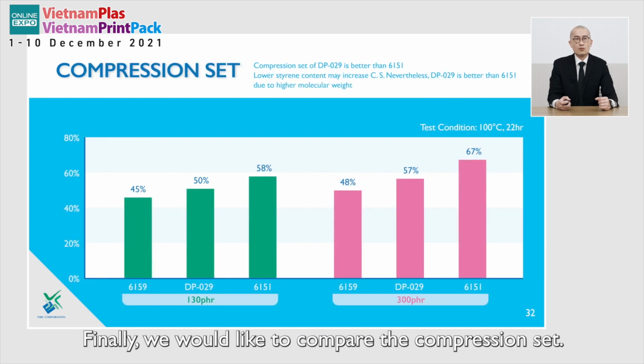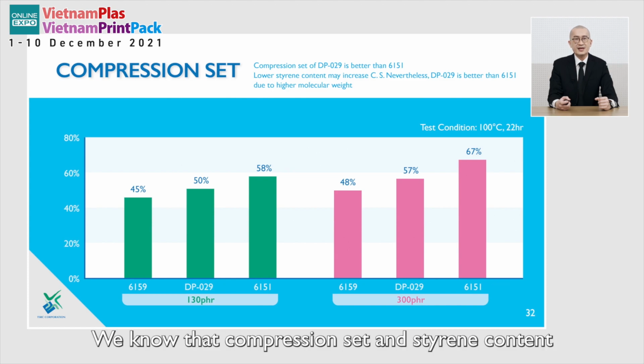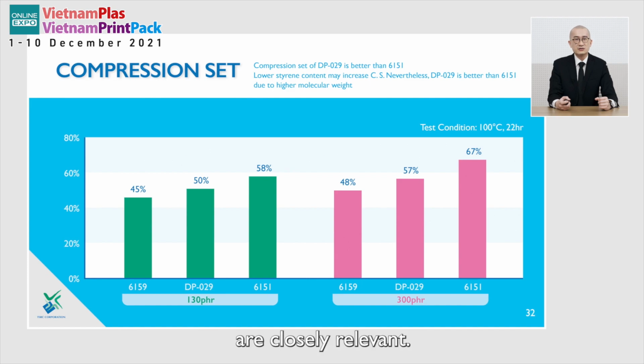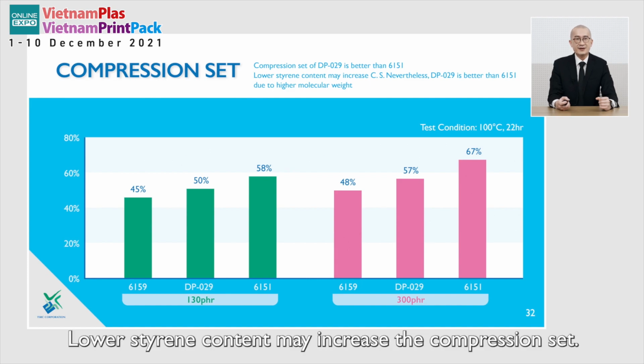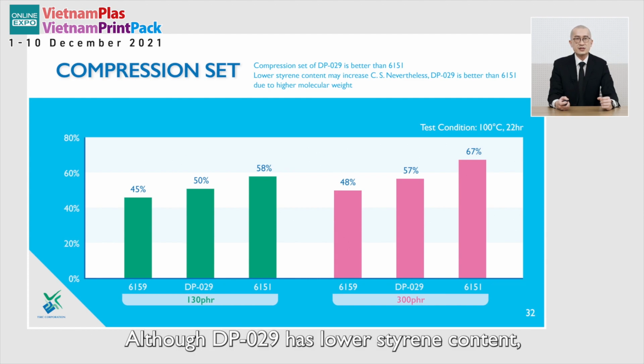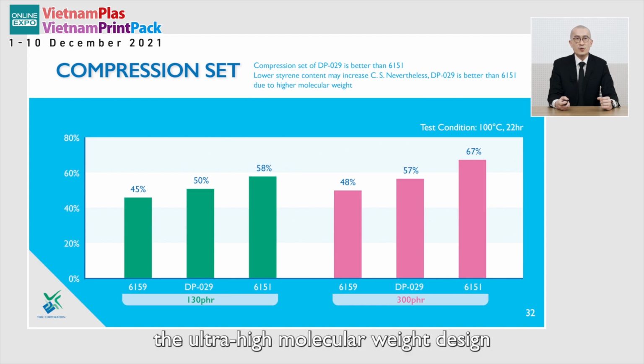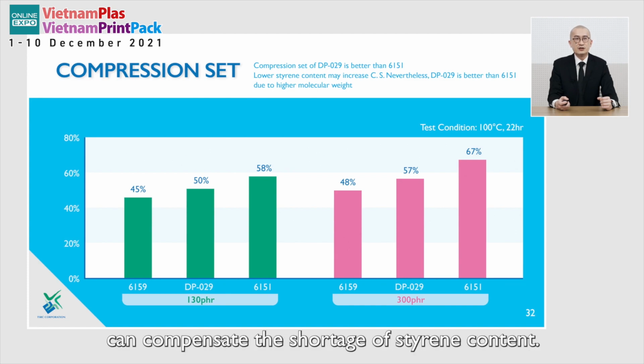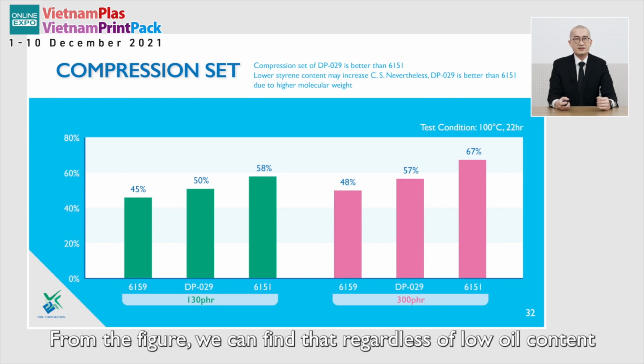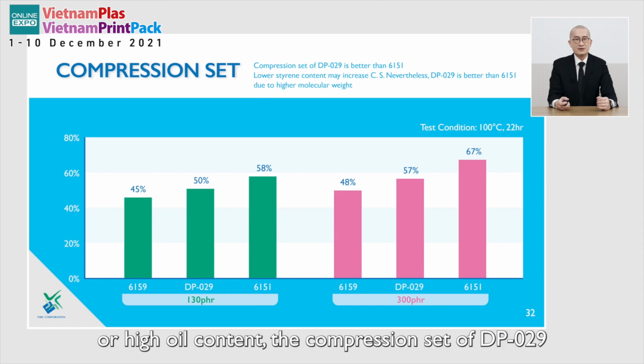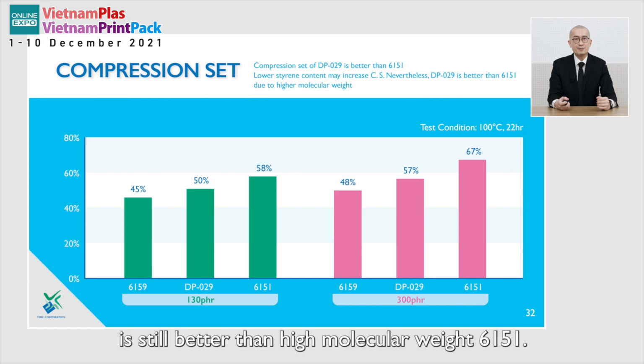Finally, we would like to compare the compression set. We know that compression set and styrene content are closely relevant. Lower styrene content may increase the compression set. Although DP029 has lower styrene content, the ultra-high molecular weight design can compensate the shortage of styrene content. From the figure, we can find that regardless of low oil content or high oil content, the compression set of DP029 is still better than high molecular weight 6151.